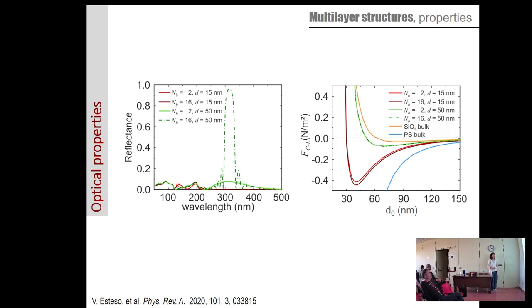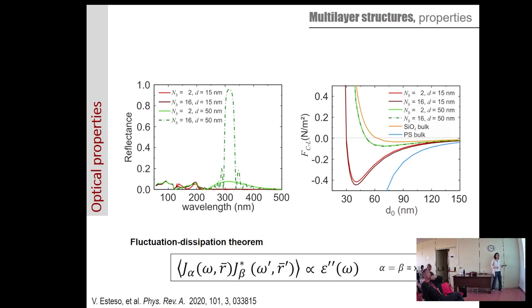And when we compute the Casimir force as a function of the separation distance, we observe that the response is modulated by that of silica in bulk and polystyrene. So we have this kind of figure, shape here. And then we observe that for thick films, nothing really happens, although we are observing very different optical properties. And for the thin films, something happens, but not so much. And actually here we do not see anything, but of course it makes sense, right? Because the fluctuation dissipation theorem, which gives us the force, says that it is proportional to the losses. So here our material is transparent, we can do whatever, we are not going to affect the absorption losses of our material, okay?